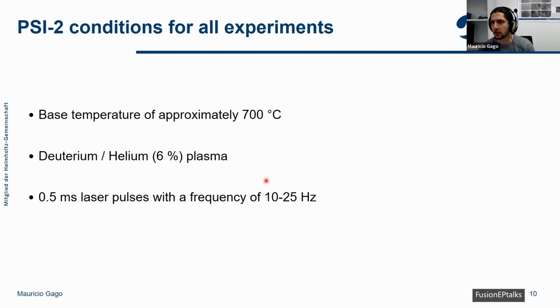And so for all the tests, to make them comparable, a base temperature of 700 degrees was used. This is also approximately, or at least a relevant temperature for the ITER divertor. Then deuterium helium plasma was applied with a 6% helium mix, which is also relevant for ITER because this is close to the percentage of helium that will be expected once the reactor is fully functioning. And laser pulses of 0.5 milliseconds were used, which is close to the pulse length of an ELM.